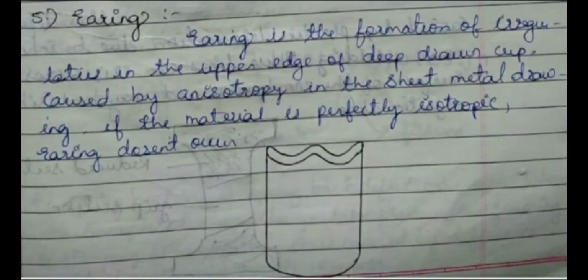Then the next defect is earing. Earing is the formation of uneven shapes on the upper edge of a deep drawn cup, caused by anisotropy in the sheet metal. If the material is perfectly isotropic, earing does not occur. So here it is earing. It is an uneven surface at the top of the cup.